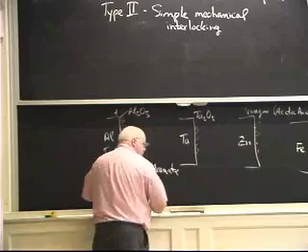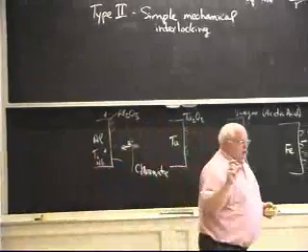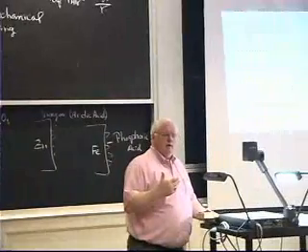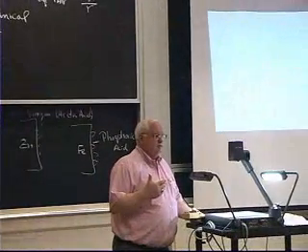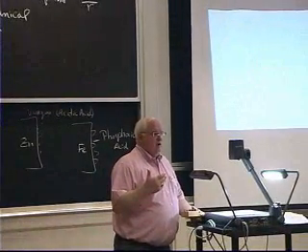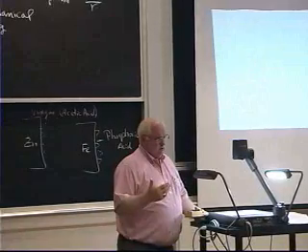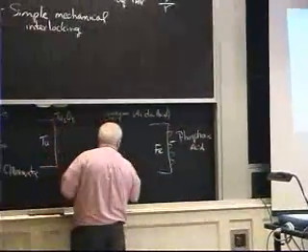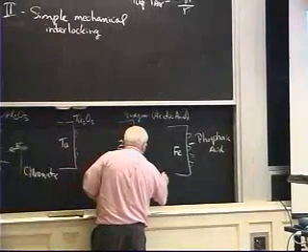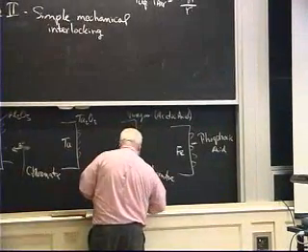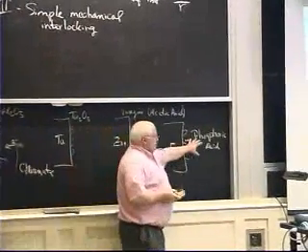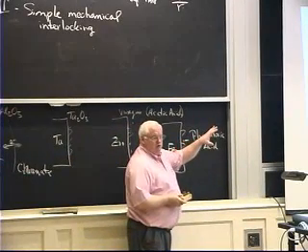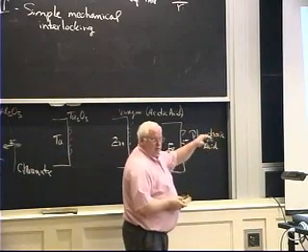Anybody ever seen a piece of aluminum that looks kind of yellowish? Or you ever seen a steel bolt that looks sort of green yellow? A galvanized steel bolt with zinc. You can also zinc chromate. You don't always have to anodize where you use electric current. I can just get a chemical reaction with phosphoric acid on steel and form something porous, just like I showed you on the aluminum oxide, on the aluminum.